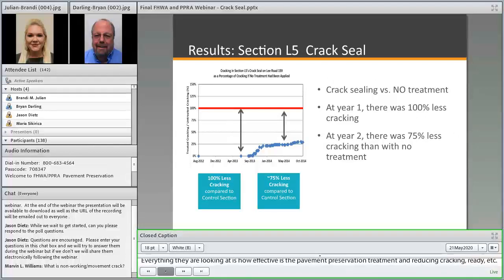So looking at this first slide, L5 was the section that they did a standalone crack seal on. They did some routing and sealing there. And as we can see on the plot graph here with the dots, after the first year, there was still 100% no cracking, and in comparison to the control, the control had cracked. There was no cracking in that section that they had put crack sealant in. It was still performing at 100%.